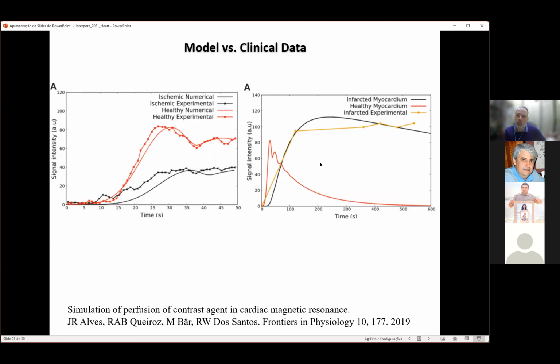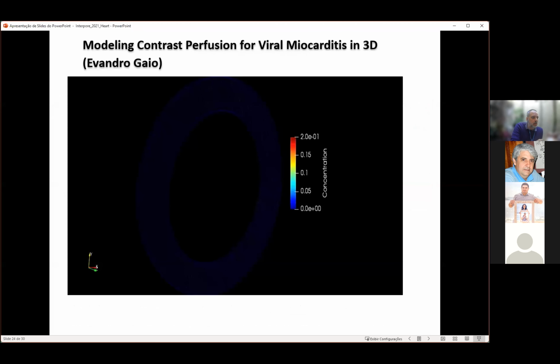And this is when you have another subject, we had infarct. The time is much longer because you have to do it twice. You have to wait around 10 minutes to do the second exam, to wait for the contrast to get trapped inside the damaged tissue. And this is, in yellow is the clinical data, and black is our experiment. So using our models, we could very well reproduce the clinical data, and we think that this kind of models will be very useful for the quantification of this kind of data.